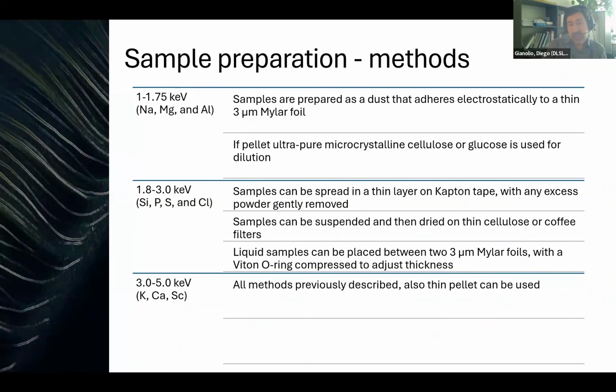So we found out that we have, between beamlines, more or less common methods for preparation, although these methods could change depending on different energies within the tender energy range. If we go towards the lower energies, it is very hard to measure samples in transmission because the ideal thickness is even lower. And the sample could be prepared as a dust that just adheres electrostatically to a thin window. Or in case of preparation of a pellet, it's very important to use ultra pure materials like cellulose or glucose, and also in very small amounts.